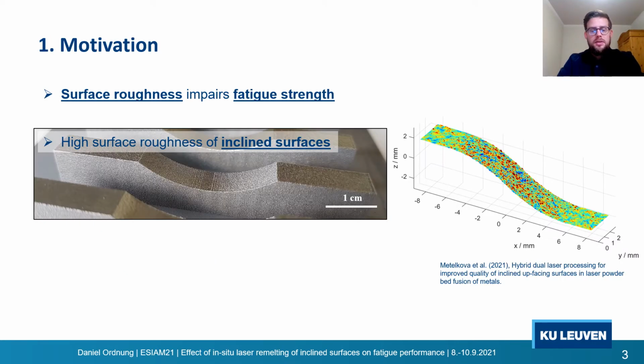So why is the surface quality of inclined surfaces important for the fatigue behavior? In additive manufacturing, there are different factors which have a limiting effect on fatigue behavior. One factor is the high surface roughness of additively manufactured parts. In particular, when we look at inclined surfaces, we see different effects which lead to a high surface roughness. There's the intrinsic staircase effect due to the layer-wise manufacturing, and then on the other hand, there's the edge effect, meaning elevated edges. These two effects are combined for inclined surfaces, leading to a high surface roughness and making them very critical for fatigue applications.